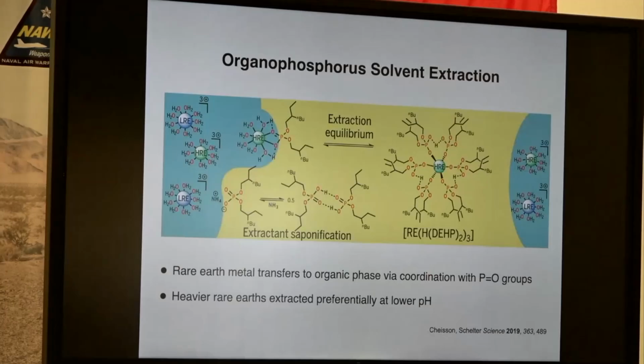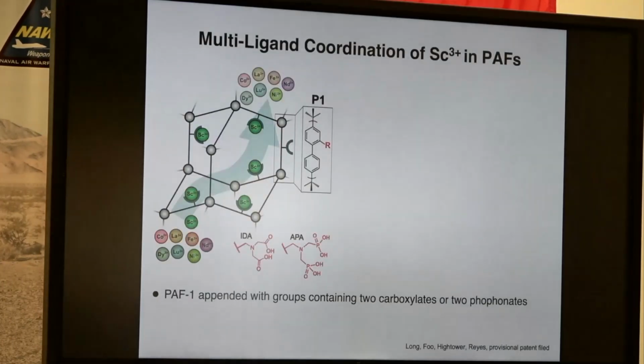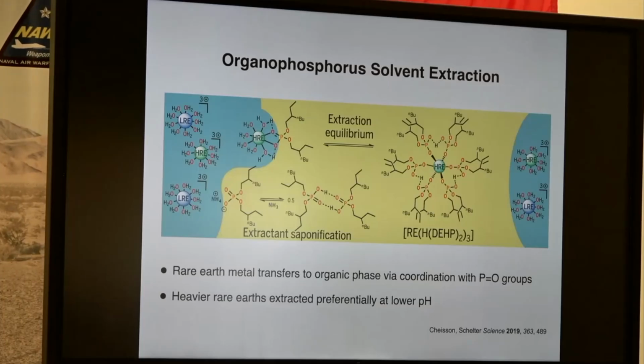Okay, so one of the hardest problems is lanthanides. Rare earth elements are very, very expensive, not because they're not abundant, but because they're very difficult to separate from each other. You have to do hundreds and hundreds of steps. And it's currently done mainly by solvent extraction, where you've got an organic layer or component that has ligands that will pull lanthanides or rare earths into that organic phase. And it does that with a very slight selectivity based on charge density of the rare earth. But the selectivity is extremely poor, and you have to do this many, many times to get a pure lanthanide or rare earth. And you'll note that these ligands, it's the phosphonate groups that are selective, these very hard donors that are binding the hard rare earth cations.